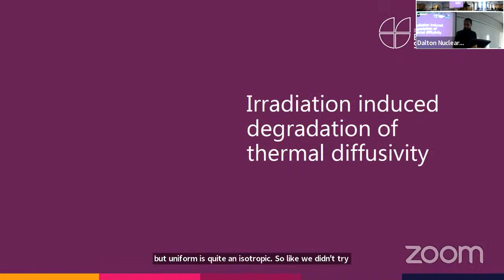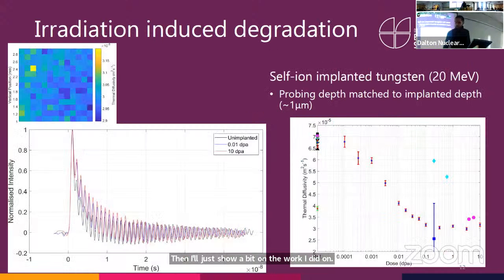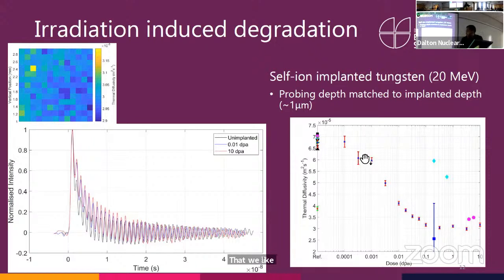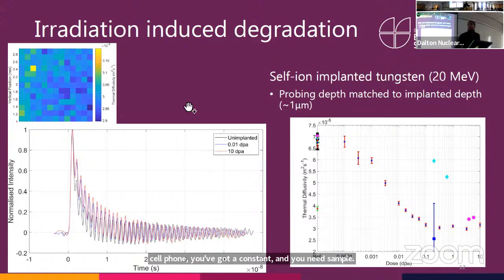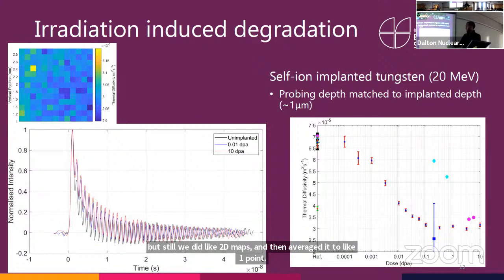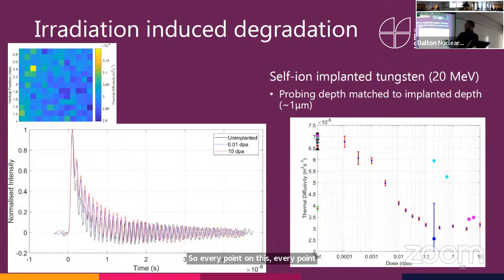So that's the first bit of it. Then I'll show a bit of the work I did on irradiation-induced degradation of thermal diffusivity, where we picked around 13 samples for different implantation doses, so self-ion implanted tungsten. Each sample was uniformly implanted, but we still did 2D maps and then averaged it to one point. So every point on this graph is from an average from a map.